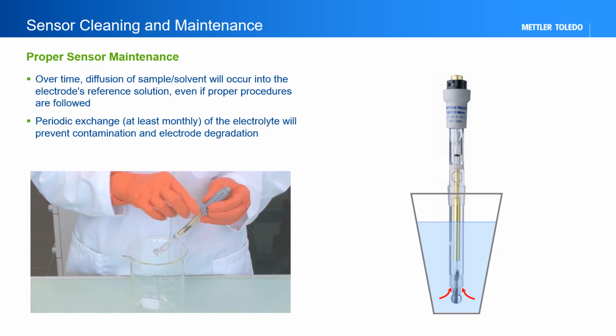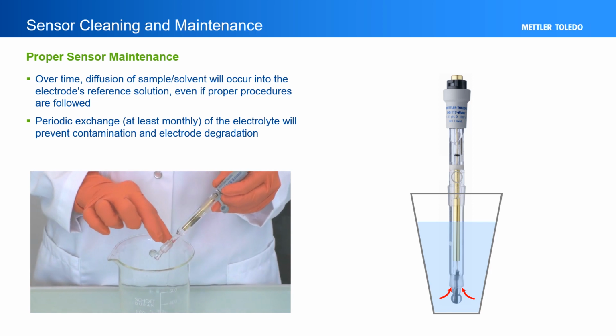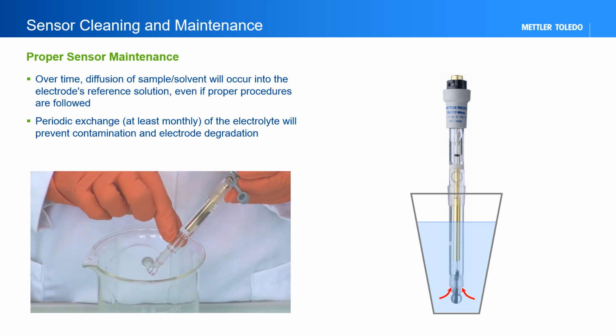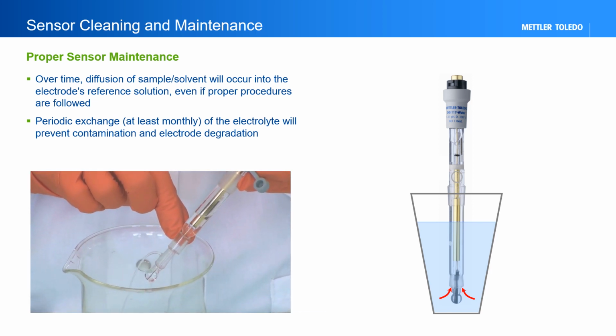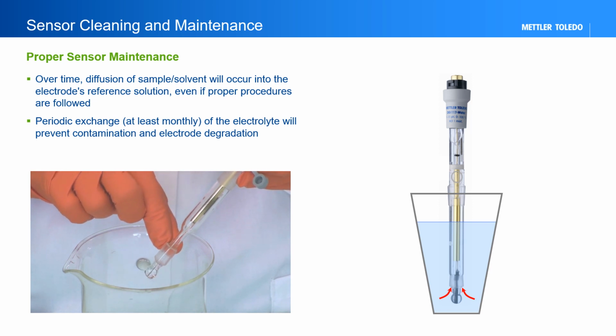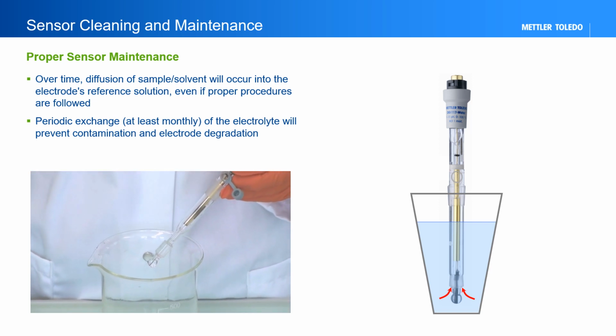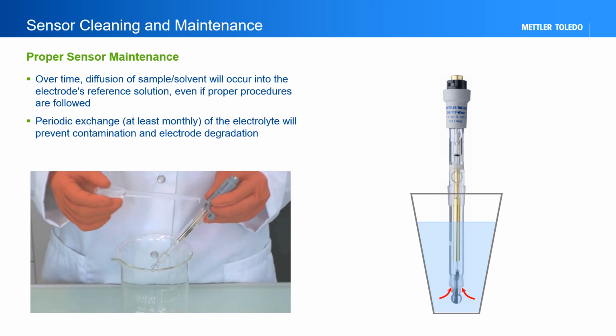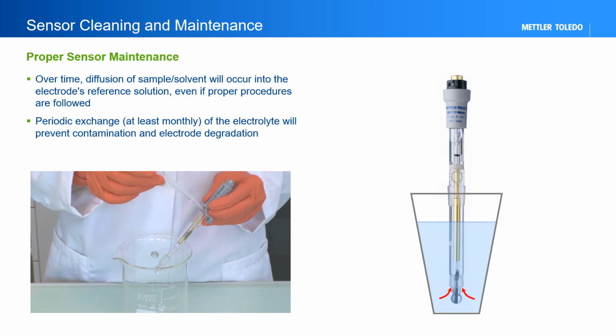Over time, even if the procedures are followed regarding the reference electrolyte level and fill port opening, the reference electrolyte will become contaminated. It is suggested to remove the reference electrolyte and exchange it once per month with normal use to avoid overall contamination and increased concentration of the reference electrolyte from slow evaporation of the solvent.